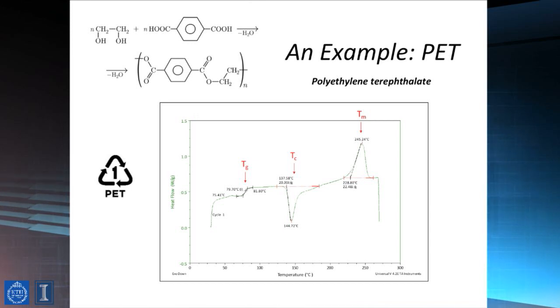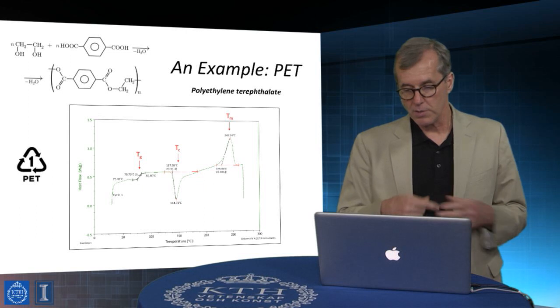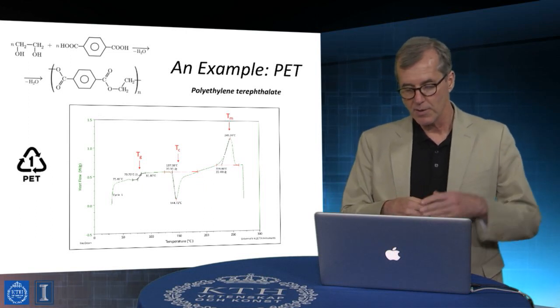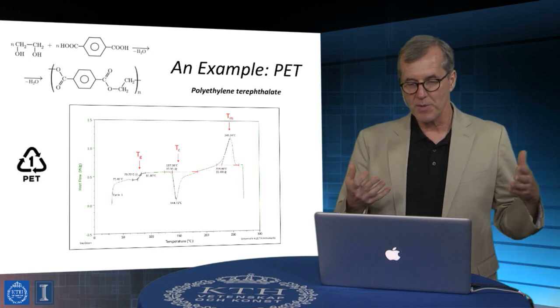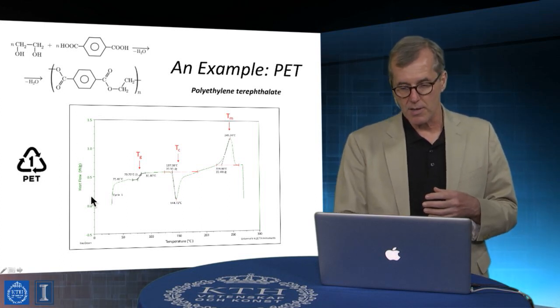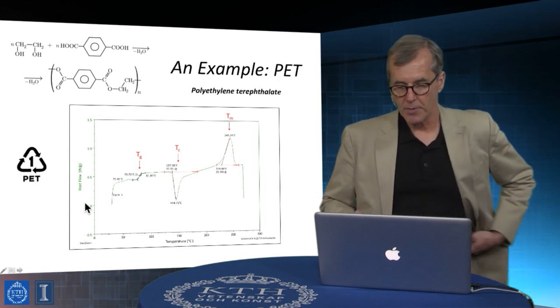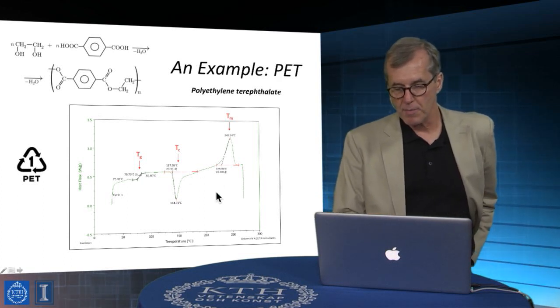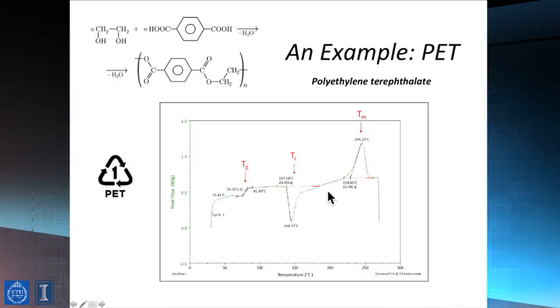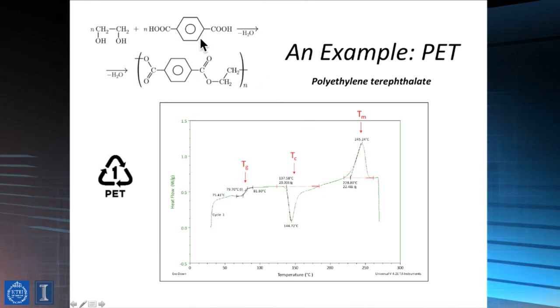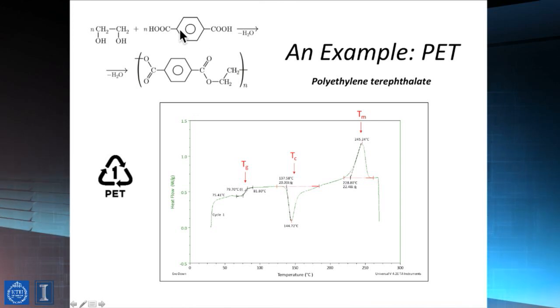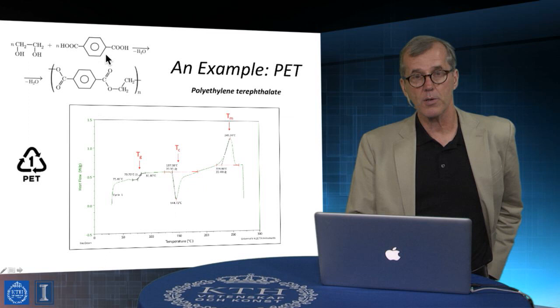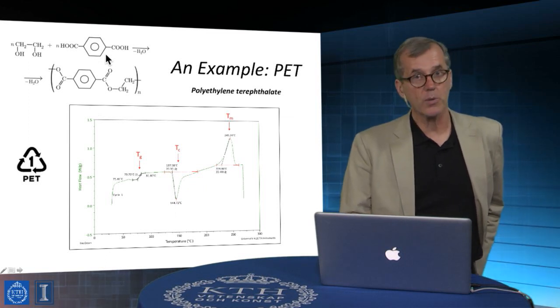And you've got to pay attention to the conventions of what corresponds to an endotherm or an exotherm, that is, whether peaks go up or down, which is something you can select by how you decide to define that axis. Right, and one of the things you note is that polyethylene terephthalate is a semi-crystalline polymer, but also a very good one. It's sometimes thought of as being something like a quasi-liquid crystalline polymer. It has very good barrier properties, which is why it's used for soda bottles, because gas permeation rates through it are very low.